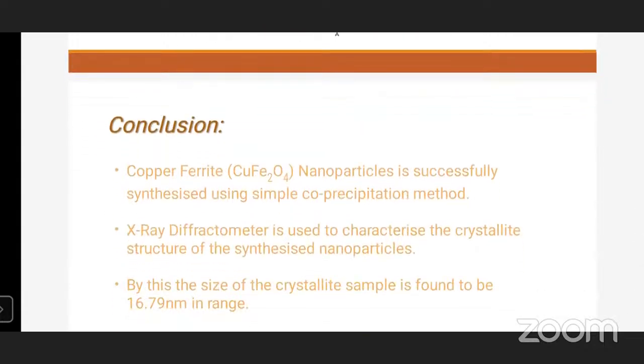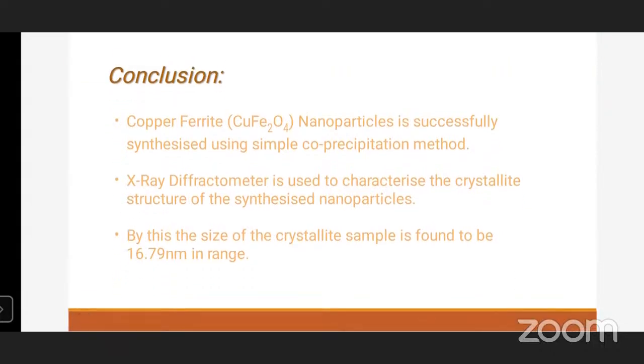Finally, the copper ferrite nanoparticles were synthesized successfully using the co-precipitation method. This is a cost-effective method and also the easiest method among all chemical methods. The X-ray diffractometer is used to characterize the crystal structure of the synthesized nanoparticles. The successfully synthesized nanoparticles were found to be 16.79 nanometers in size, which is a good range for comparison. Thank you, sir.